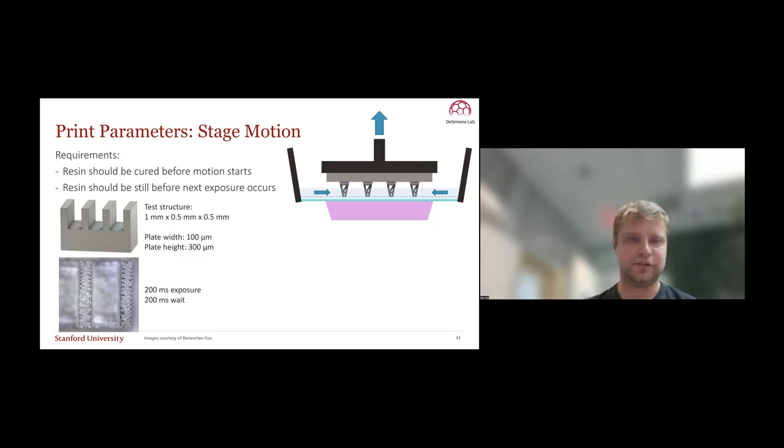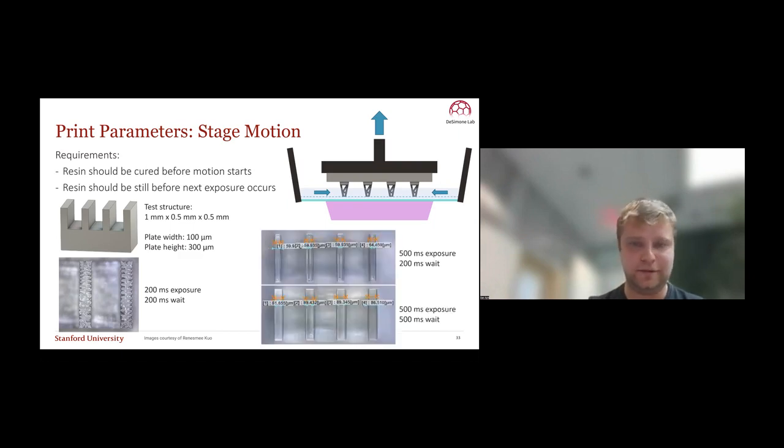And so just to illustrate what happens if you don't wait enough, you actually get this sort of canyoning feature shown on the bottom left, where your resin literally creates canyons in your part. If you wait long enough, then your part comes out as you want.